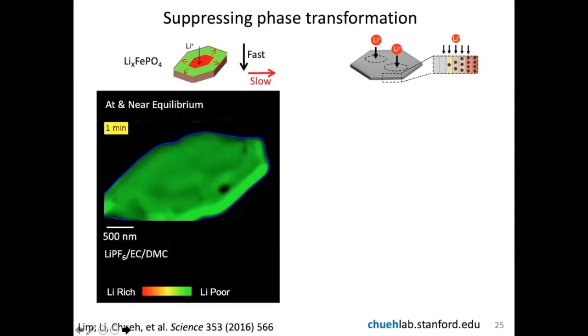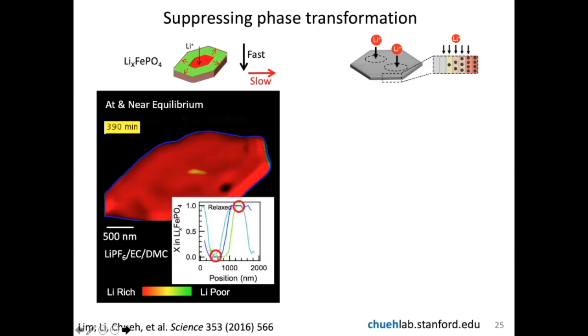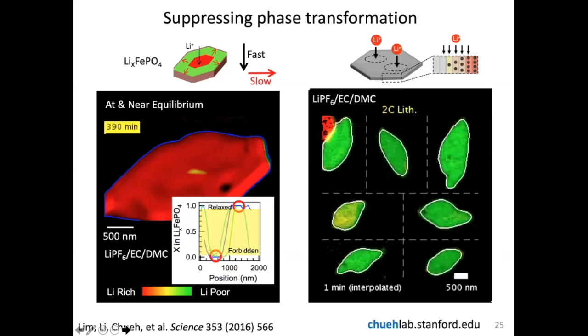And this is what you expect from thermodynamics. You don't see any composition within the miscibility gap. If you do this experiment in situ, you can also see the moving front. So this is what happens when you're at a C over 5, C over 6 rate, you have classical phase separation. But as you increase the rate of lithium removal and insertion, the material actually breaks thermodynamics here. And instead, you see the appearance of composition that's within the miscibility gap.